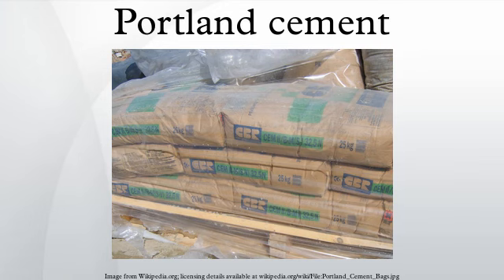When water is mixed with Portland cement, the product sets in a few hours and hardens over a period of weeks. These processes can vary widely depending upon the mix used and the conditions of curing of the product, but a typical concrete sets in about 6 hours and develops a compressive strength of 8 MPa in 24 hours. The strength rises to 15 MPa at 3 days, 23 MPa at 1 week, 35 MPa at 4 weeks and 41 MPa at 3 months.